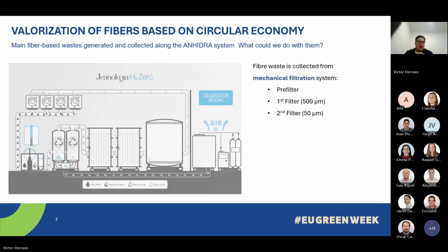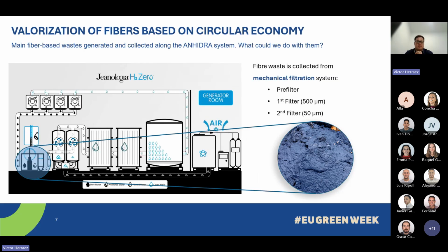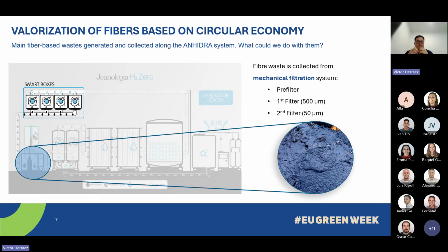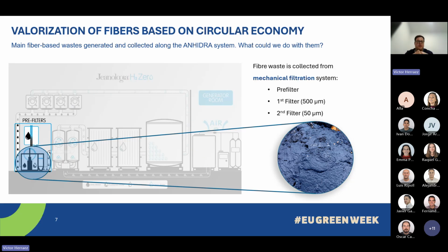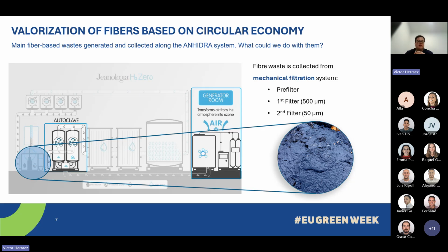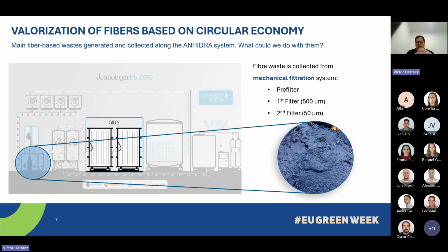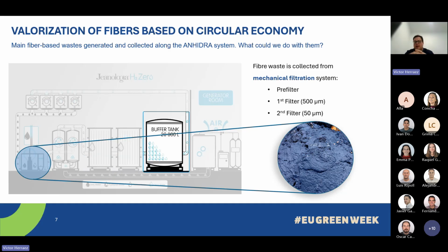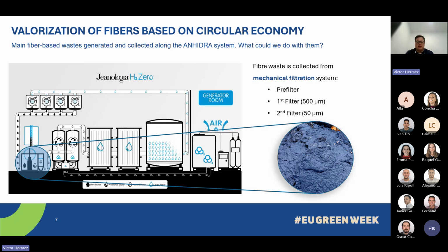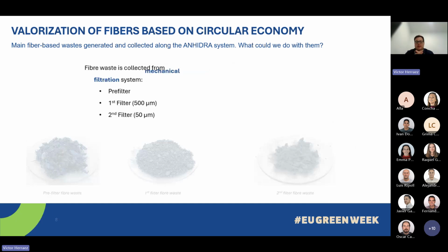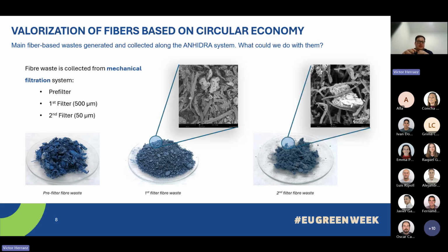So one of the downstreams that we get from this treatment system is fiber waste from all of the garments, with the abrasion of the stones and the oxidants that we put in. We get this waste, which is mainly composed of cellulose, but it also has other impurities such as stones from the stone washing treatment, and other metallic parts that can be on the jeans or in the jackets that have been treated. So in this stage, we collect many different wastes depending on which filter we take them in.